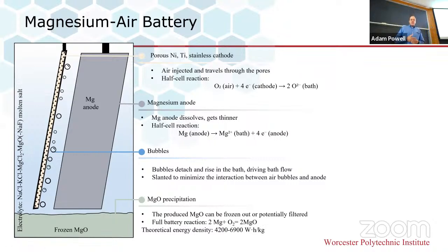The theoretical energy density is extraordinary. And the practical energy density is somewhere around 1,500 to 2,000 watt hours per kilogram, which is about 10 times lithium ion. Then the problem is you have to get this magnesium oxide out of the molten salt. So a proposal for that was, let's try freezing it from one side and see if that works. And sure enough, the first time Maya tried an experiment, it worked.